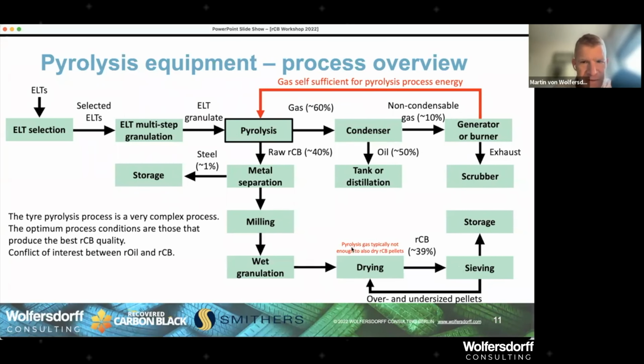The pellets, you could do a whole workshop just about pellets and the hardness of the pellets. But then we have about 39% still in the pellet. After drying, actually the wet granulation, you have 50% moisture in the pellet, and that's the reason you need to dry.